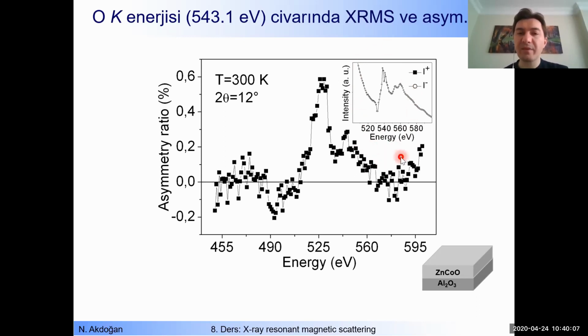Then I can change the energy in order to see the oxygen K shell. So I apply magnetic field in that direction and I measure the intensity plus. I change the direction of the magnetic field and I measure intensity minus. What do you see here? There is no difference. You cannot see anything in the XRMS signal, right? But if I plot an asymmetry ratio from those two signals, I can see this information. The asymmetry ratio clearly shows us that we have a magnetic signal from the oxygen.